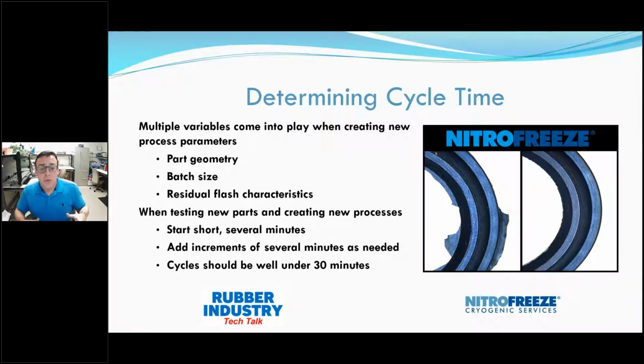Okay, so when we're running samples, we always say the more the merrier, because if I run one piece in a basket, that is not going to be representative of what I can do efficiently. And it's not going to really help me quote out a process either. So we ultimately like to get, for example, a box of parts, and we like to do some experimentation, because that allows us to get a good feel for the batch size. A pretty good rule of thumb, and we use part counters to determine this, is to basically cover the bottom of the basket.